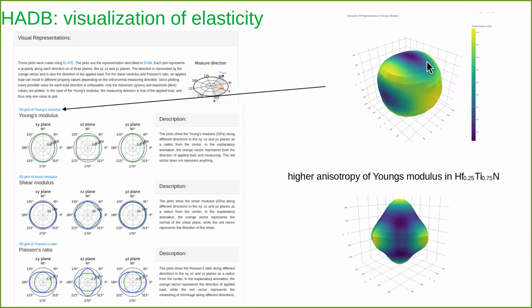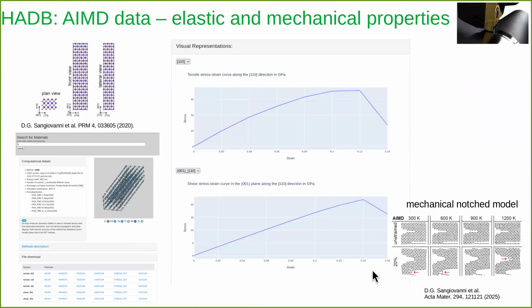In the case of niobium aluminum nitride, we got a very nice almost spherical model, which is shown here, or mostly circular behavior of the different moduli. You take another alloy, then you will have more anisotropy, which is represented here. Okay. Leaving the elasticity, we can go towards the ab initio MD data that we are storing here. We take a long, elongated superstructure, so it is like a pillar in the code, with repeated pillars.